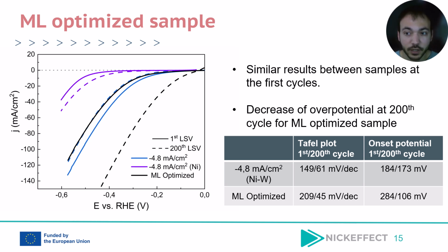As you can see, at first both have similar Tafel slope and overpotential. But after 200 cycles, while the blue sample degrades a bit, the machine learning optimized sample shows even a better performance than the initial one. Having said that, both samples are much better than the pure nickel electrode deposited sample in purple.